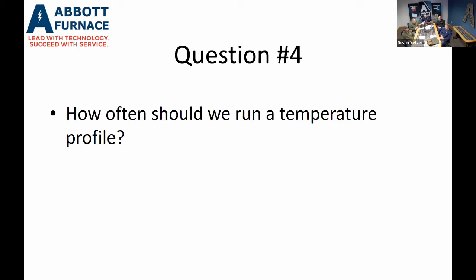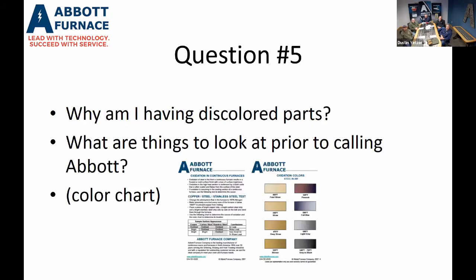Okay, thank you, Dustin. Question number 5 is for Matt. Why am I having discolored parts? What are things to look at prior to calling Abbott? This kind of goes back to what Brian touched on. We get our discolored parts for a bunch of reasons. Looking at this color chart, which is very helpful when you have discoloration of your parts coming out. If you see like the yellow color, 400 degrees, that's more or less coming out of the back of the furnace. By going by the color of the part, the temperature, you can actually look at your temperature profile and figure out where that's happening. The lighter the colors are,